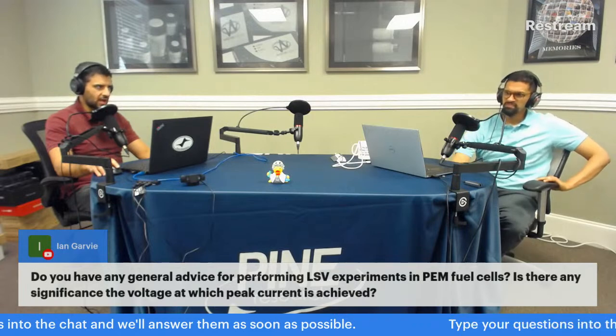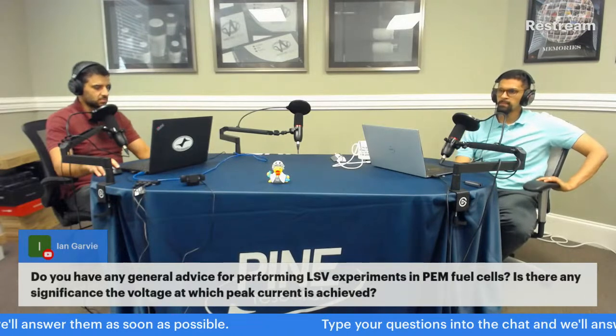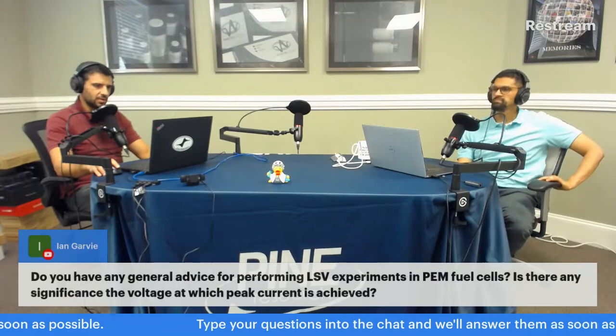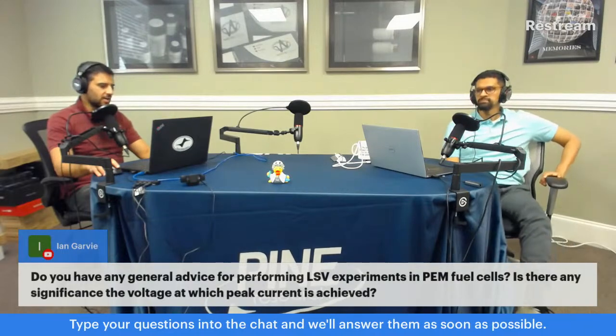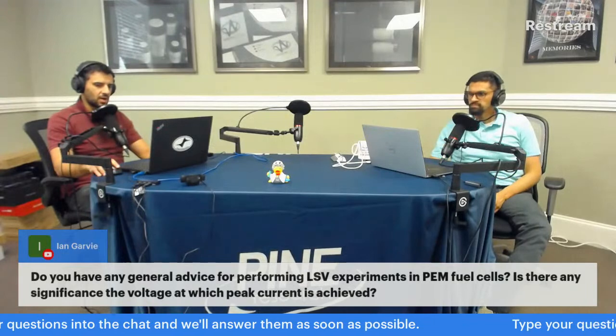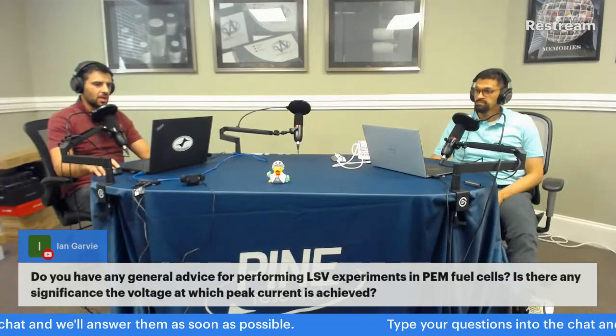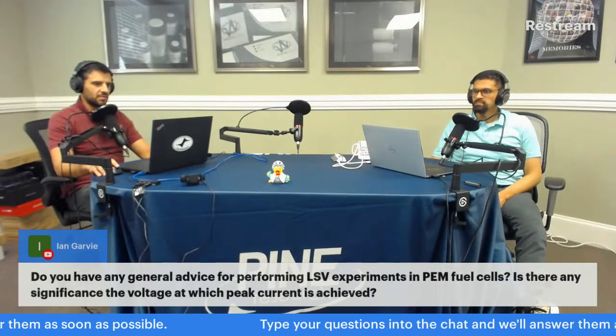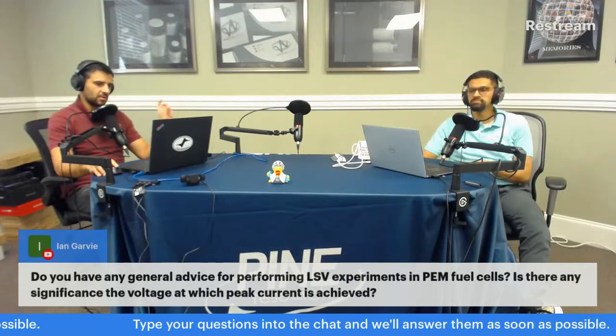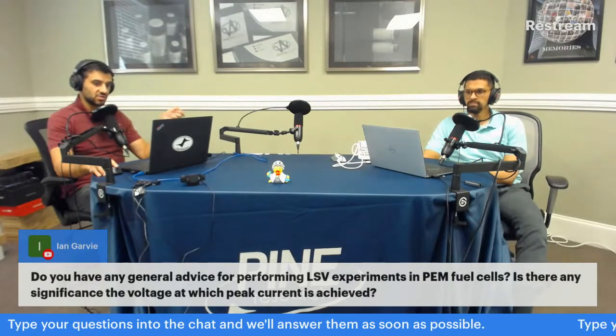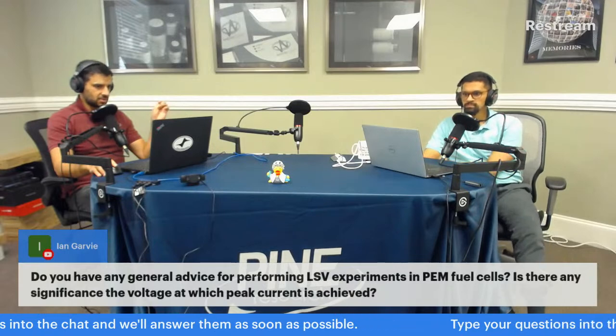OCP first. Yeah, well, you run OCP, so make sure your fuel cell has a volt. If you're doing a PEM fuel cell, it should be about a volt. The theoretical is 1.2, and most likely you won't get that, but you'll get 1 or 1.1. And then typically you're going to do an LSV experiment from open circuit, which is 1 or 1.2, down to about 50 millivolts. Go slow.